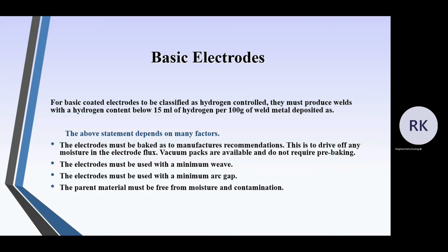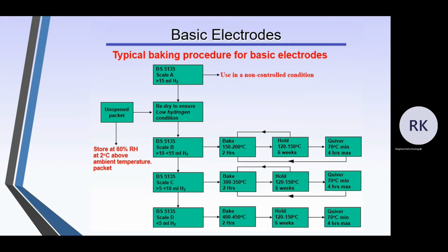So the above statement depends on many factors. The electrode must be baked according to the manufacturer's recommendation. This is to drive off any moisture in the electrode flux. Vacuum packs are also available, which do not require pre-baking. The electrode must be used with minimum weave and minimum arc gap, and also the parent material must be free from moisture and contamination.